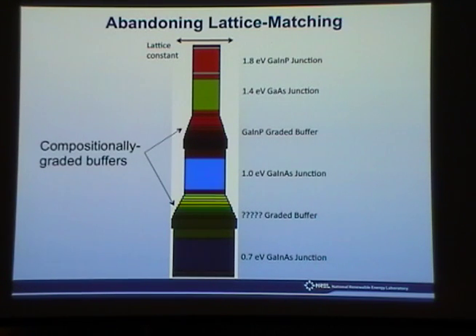It's chemically difficult to integrate some of the amorphous materials into the III-Vs as a matter of growth. So we grow these by MOCVD, metal organic chemical vapor deposition. Sometimes it's called vapor phase epitaxy. There's a bunch of names, but it's very hard to have a system that can grow the III-Vs at the purity that you require and grow the amorphous materials. Okay. There are proposals to use other material systems out there.